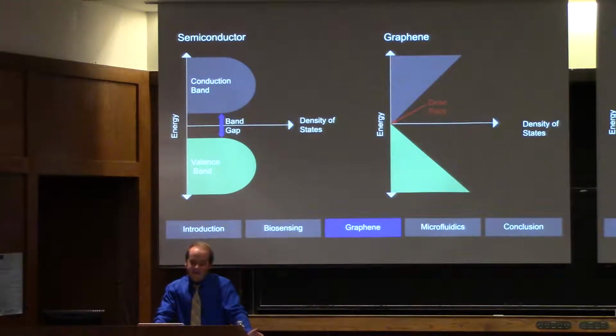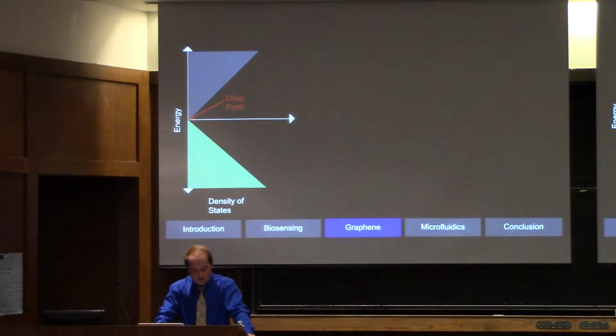And this is called the Dirac point. At this Dirac point, the conductivity is at its minimum, because conductivity is directly proportional to the density of states. You can think of it this way: the more states available, the less energy it will take to excite an electron to the next state, and the higher the conductivity will be. The minimum conductivity at the Dirac point results in a maximum resistance, because as you can see here, the two are inversely related.